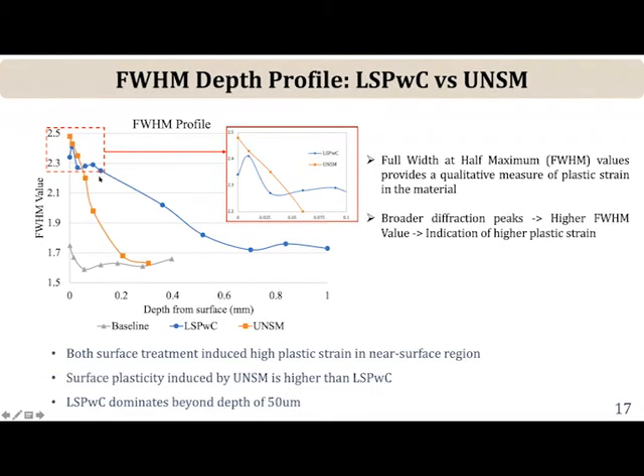So what you notice here is this is the full width half max of the diffraction peak as a function of depth. And what you see here is that in the case of UNSM, when you blow this up, the dislocation density, as I mentioned, with UNSM are much higher than compared with laser shock peening. The crystallite sizes are also much finer. Okay, you can get almost 20, 30, 40 nanometer size crystallites at the surface, and that gives you a much greater extent of broadening compared with the case of LSP. And interestingly, of course, even with LSP without coating, you do have a fair amount of broadening at the surface. At the surface, it's a little lower, but the dislocation density just beneath the surface is actually quite high. Okay, so beyond about 50 microns or so, there's much more plastic strain with LSP compared with UNSM.